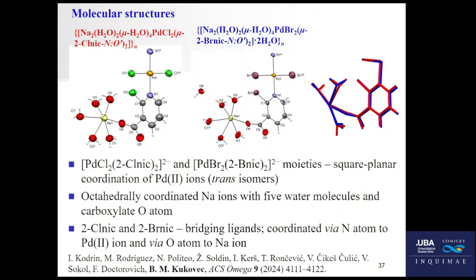In this figure you can see the asymmetric units. The first one is the 2-chloronicotinic acid polymer, and the second one is 2-bromonicotinic acid. Here is the overlap. You can see they are quite similar. The difference is that the bromide is coordinated to palladium in the bromonicotinic one, and the chloride in the chloronicotinic one. Sodium ions are octahedrally coordinated, with five water molecules and the carboxylate oxygen from nicotinate, and the palladium is coordinated by the nitrogen atom from the aromatic ring. Both 2-chloronicotinic and 2-bromonicotinic are bridging ligands here. They bridge sodium and palladium. As I mentioned, these are just the asymmetric units.